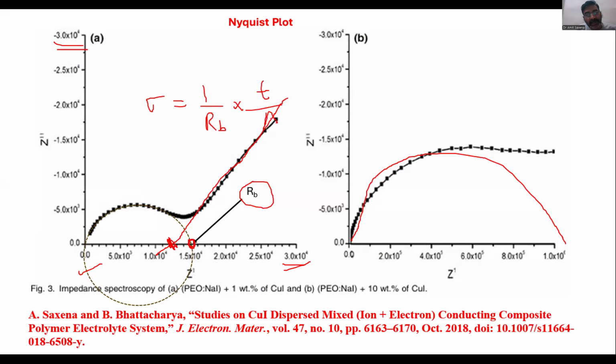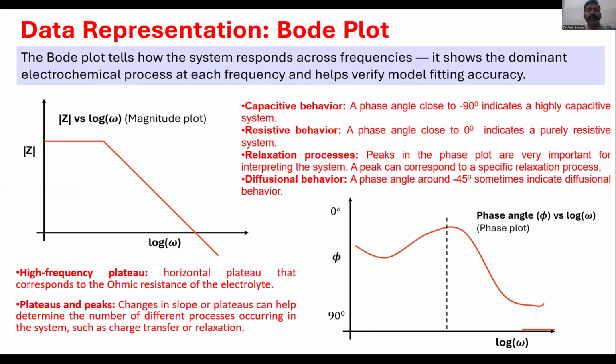Thickness is the polymer electrolyte film which you have prepared, and area is the sample electrode which you have used to measure the impedance spectroscopy sample, right? So by this way, you can calculate the conductivity, and based on the conductivity, you can calculate the value of N and mu.